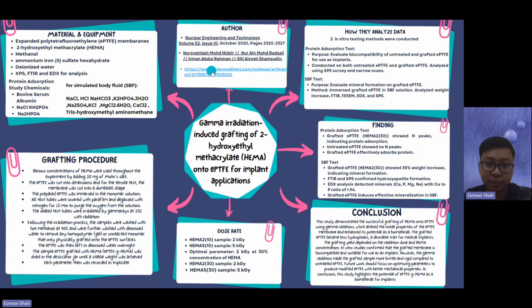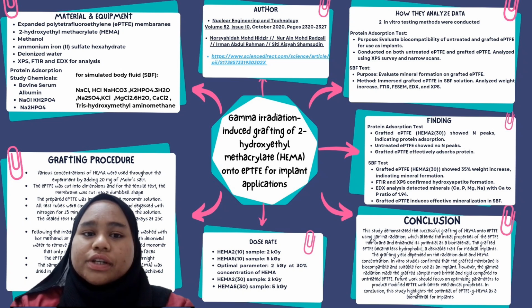It's recorded 3 times. So the dose rate used for the experiment for the HEMA 2 sample is 2 kGy, HEMA 5 sample 5 kGy. The optimal parameter is 2 kGy at 30% concentration of HEMA. HEMA 2 30 is the sample of 2 kGy and HEMA 5 30 is the sample of 5 kGy. So, 2 in vitro testing methods were conducted in this experiment to analyze the data.